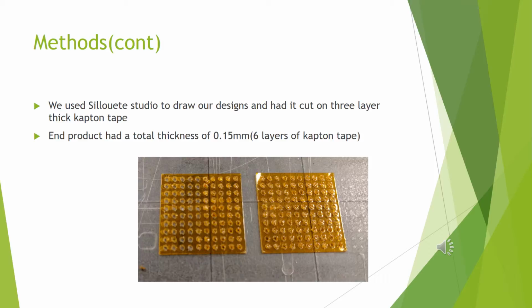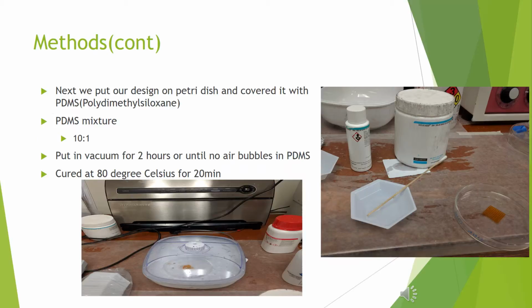To make the mold, we decided to use Kapton tape and Silhouette Studio to draw and cut out the molds. We cut the molds out of 6 layers of Kapton tape. This part of the process was the most tedious and exacting because it was easy to rip the tape. We then put the cutout Kapton tape onto the bottom of a petri dish and used PDMS, a silicon-based polymer, to create the mold. To make the PDMS, we had to mix a pre-polymer and a curing agent in a 10:1 ratio. Upon mixing and pouring, we put the mold inside of a vacuum for 2 hours, or until there were no more bubbles in the mixture.